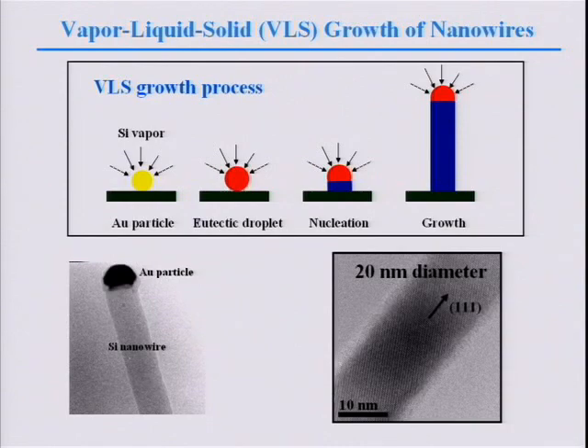If you look at the phase diagram, when you mix gold and silicon together, they melt at a really low temperature. Gold alone has a melting point of about 1,000 degrees C, and silicon alone has a melting point of about 1,400 degrees C. But when you mix these two together, the melting point is 360 degrees C. It's really, really low. So using this property, at about 400 degrees C, you can add silicon into gold and make a liquid droplet. If you keep adding silicon into this droplet, the silicon supersaturates, and it's going to nucleate and grow into a one-dimensional nanowire structure. It's this tiny size which defines the nanowire structure.